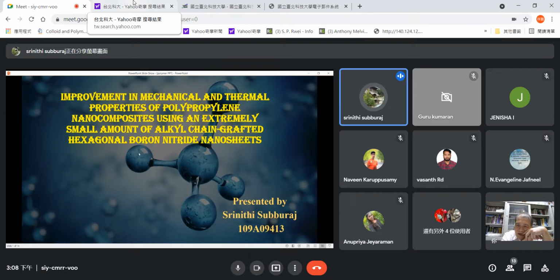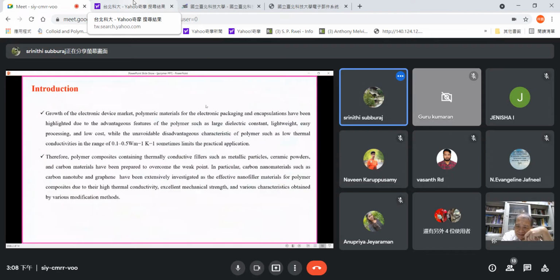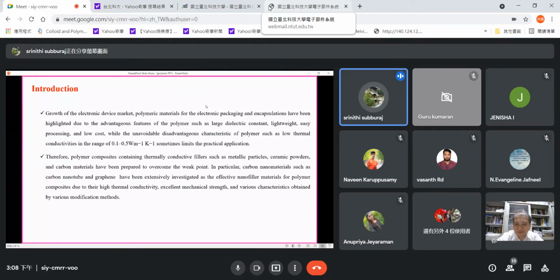Now I'm going to present improvement in mechanical and thermal properties of polypropylene nanocomposite using an extremely small amount of alkyl chain grafted hexagonal boron nitride nanosheets. In this study, hexagonal boron nitride nanosheets grafted with an aliphatic group were prepared by a sonication alcoholysis reaction using hexagonal boron nitride with 1-dodecanol, and polypropylene nanocomposites. These nanocomposites showed improved mechanical and thermal properties.